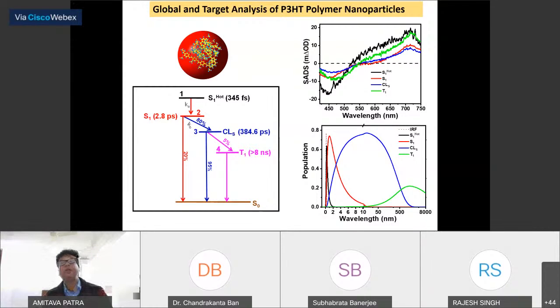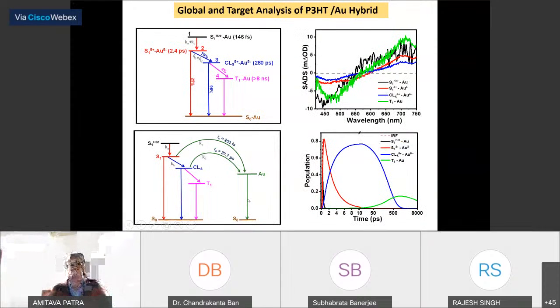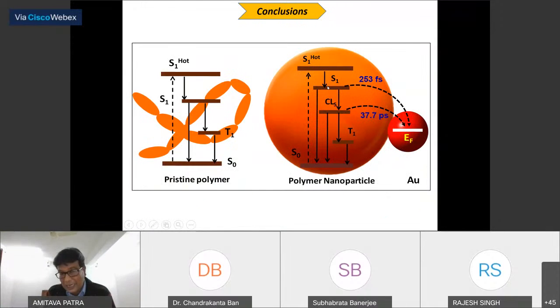We tell what is the mechanism, how the electron transfer or energy transfer takes place from the polymer to nanoparticle. All the detailed mechanism, detailed relaxation process we understood by using the transient spectroscopy as well as by fitting global and target analysis. Most of the time we say the excited state energy transfer takes place. But what is it? It comes from S1 state or from CL state. Here we have observed from S1 state it can go to the gold nanoparticle or from CL state. So all the quantitative data we have done by using the spectroscopy.